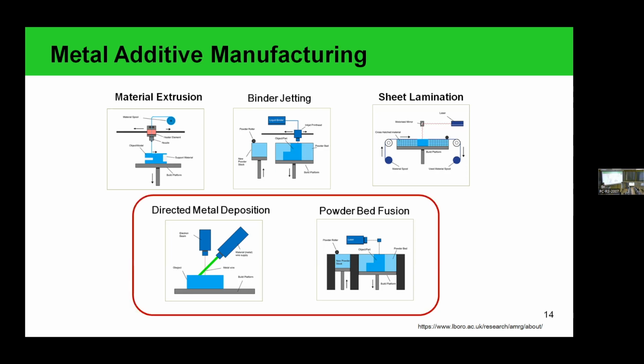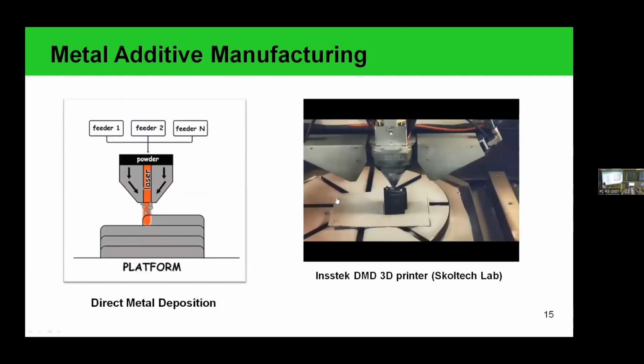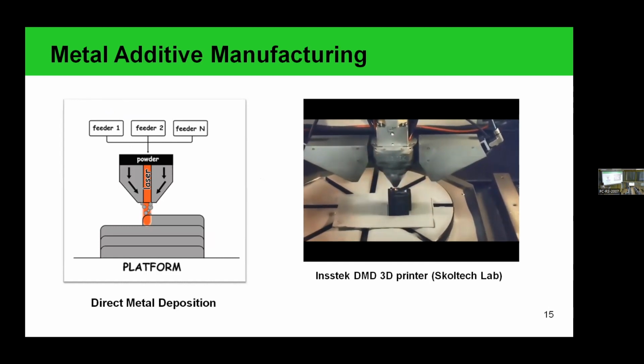And only two additive manufacturing techniques, direct metal deposition and powder bed fusion, provide the possibility to fully melt the materials and to manipulate the alloy composition. The first is the direct metal deposition technique. We can use several feeders, so we can simultaneously print with different materials, and we apply our powder in the same place. We heat it with the heat source. It can be a laser, it can be an electron beam. And this is how we print our solid part layer by layer.